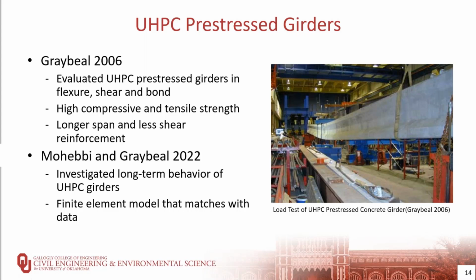In addition, due to the inclusion of the steel fibers in the UHPC matrix, it has the potential to reduce the required shear reinforcement and require only supplemental reinforcement to control bursting and transfer stresses in the end regions caused by the large prestressing forces needed for long span girders. Mohebbi and Graybeal investigated long-term behavior of UHPC girders, where a finite element model was also created to match the data that they got.